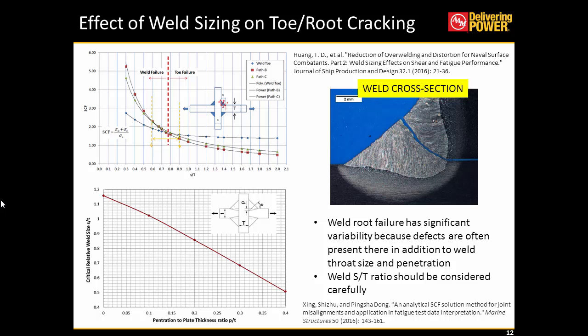So what this means is that the size of the weld has a critical part to play in first predicting the life, because the weld toe failure is the most common failure mode, most preferred failure mode, I should say, because there are so many inherent defects along the throat, along the root, which we might not be able to represent very well. So we should try to model for the weld toe failure.